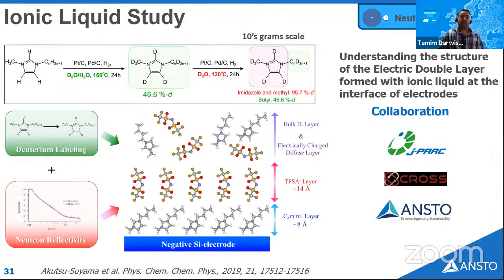at large scale in collaboration with Cross and JPARC. And we were able to deuterate the tail and the head at different levels of deuteration in order to allow studying by neutron reflectometry the electric double layer and how the ionic liquids are assembling on the interface.